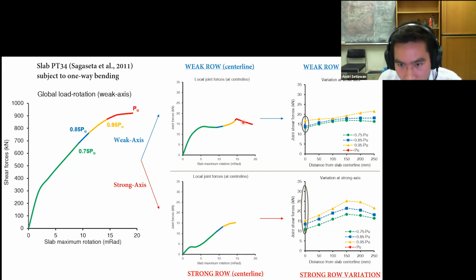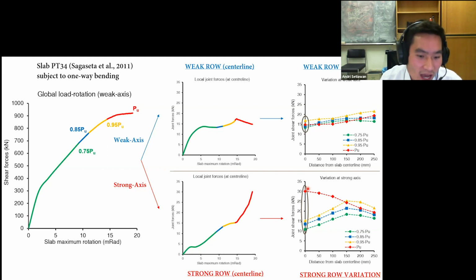But now we can see in the weak axis, the joint force has softened. So this part has failed locally. We can see in the right figure, the red dashed line is actually lower than the yellow dashed line, which means that all of the joints here are already in the softening part. And we are expecting the joints in the strong axis to take over the forces. And yes, it does. The joint at the strong axis will take care of the load that is redistributed from the weak axis. And we can see in here nicely that the joint at the center line, which has the smaller rotation, at the end of the failure load will have the highest portion of the force because the resistance there was highest at the end.